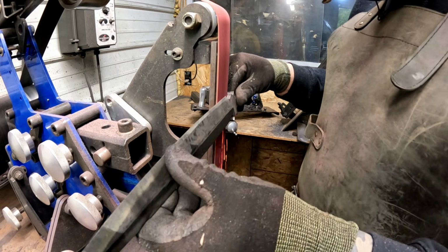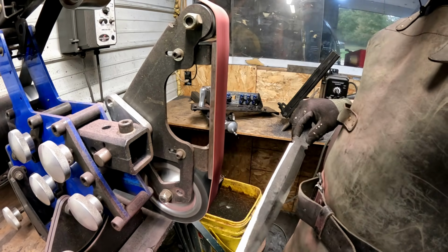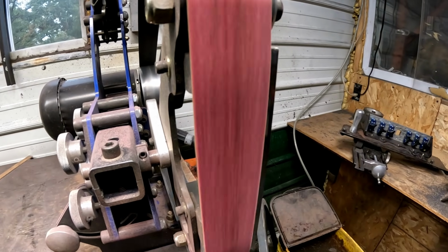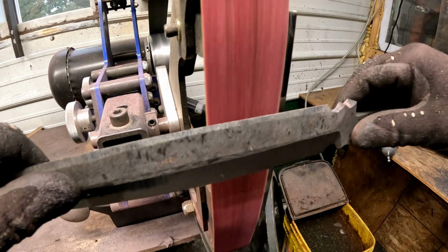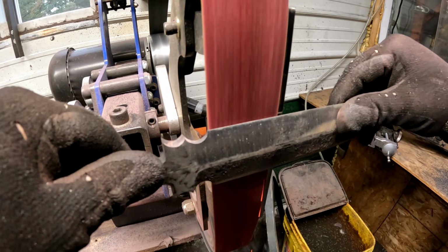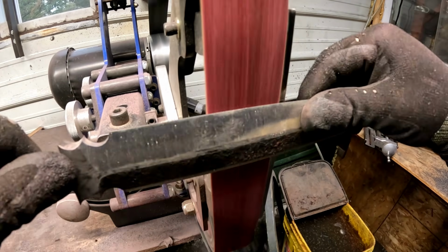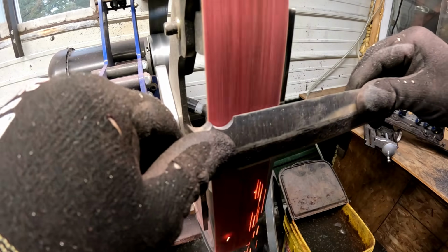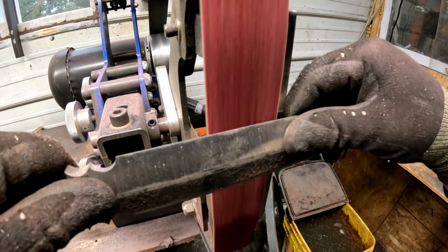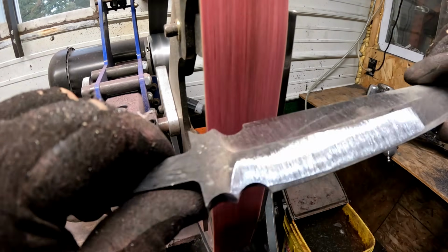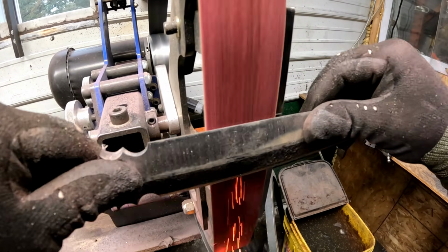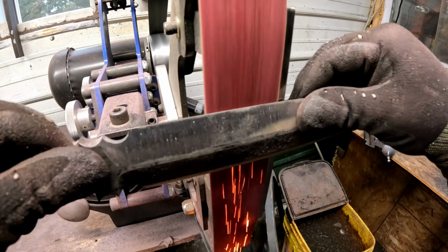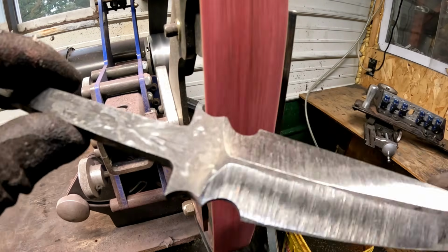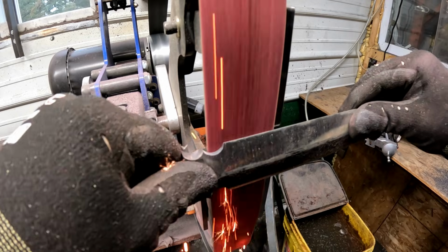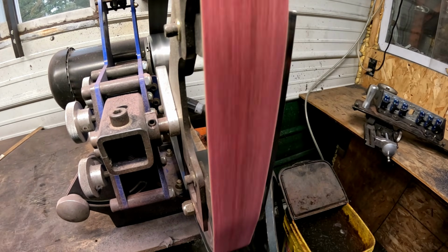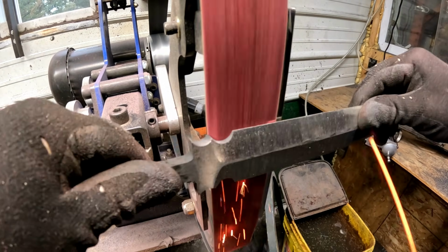Here's the science. Thin steel at the point has way less mass to soak up heat. The ricasso, thick, beefy, laughs at a warm belt. The tip, skinny, pointy, heats up faster than a gossip in a hair salon. Add a fine belt spinning at 2,000 RPM, and that localized hotspot can climb past tempering temps in seconds, drawing the hardness right out, leaving you with a tip that folds on first contact. Dunk often, keep it cool, save the temper. One lazy pass and your dagger's now a letter opener with commitment issues.